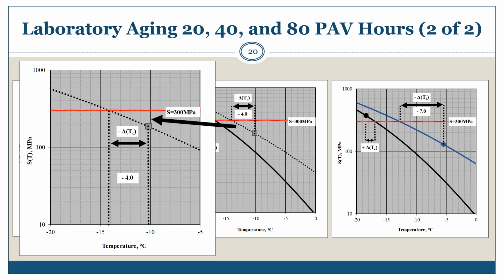I would like to draw your attention to some important points. Often we are asked, why do polymer modified asphalts sometimes show issues with delta Tc, but do not show issues with cracking? With this expanded figure, notice what happened to delta Tc with aging. It went from positive to negative, S controlled to M controlled, or stiffness controlled to relaxation controlled, and we approached more negative values of delta Tc.